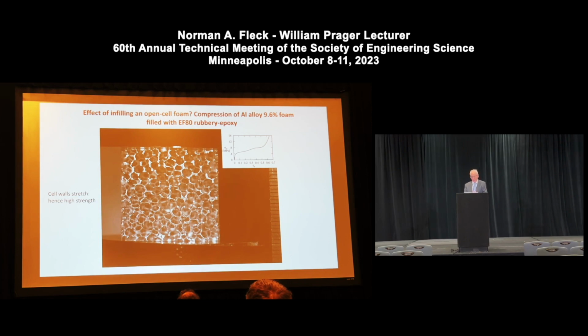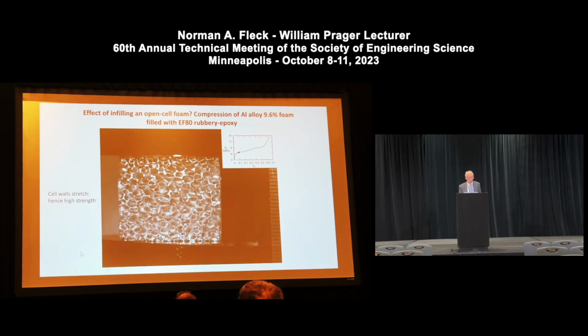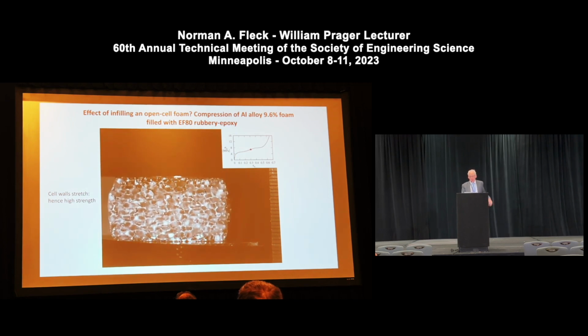Here is essentially a Kelvin foam in the form of an aluminium alloy metal foam, which is filled with essentially an incompressible rubber epoxy. Here's the response. And you can see that what I described in terms of a stable hardening and uniform response takes place. Some of the rubber comes out from the edge of the specimen, but essentially the rubber is behaving at constant volume, changes the deformation mode, and the lattice is stable and stiffening. This is an open cell Kelvin foam, as opposed to the closed cell Kelvin foam, which I showed in the simulation.